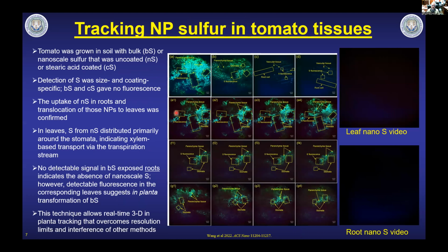So where have we used this? This was a paper we published in 2022 where we applied different forms of sulfur to soil: bulk sulfur as well as sulfate, and then nanoscale sulfur in coated and uncoated forms. And what we found with this technique, two-photon microscopy, is that the detection of sulfur in the plant was dependent both on the size and the coating.